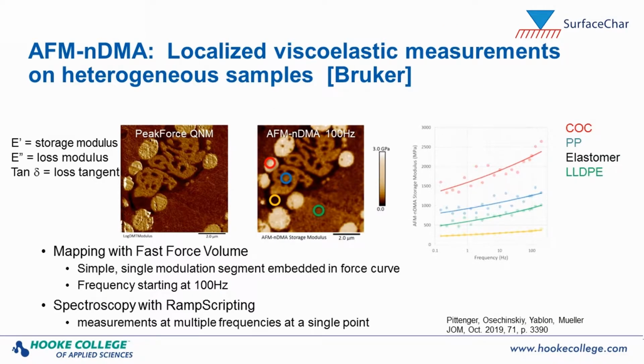So the idea behind AFM nano DMA is now to make localized viscoelastic measurements on heterogeneous samples. And again, this was a technique that was released by Bruker this year. So the idea is the following, that you will image your sample using a standard AFM imaging technique. This is a sample with 4 different materials, a polymer blend of a cyclic olefin copolymer, this here is polypropylene, this here is polyethylene, and then this dark region here is the elastomer.